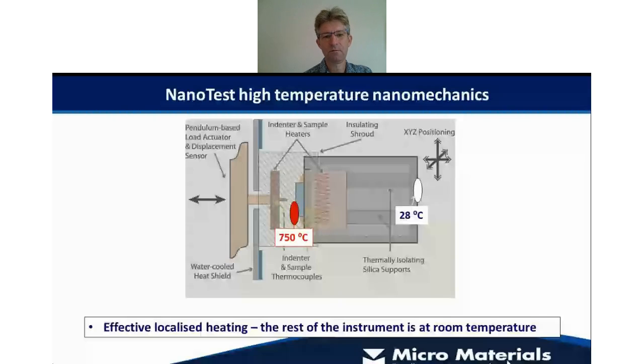We did a test at 750 degrees, and we can put another thermocouple at the back of the hot stage, and we can see that's about 3 degrees above room temperature, so that's almost exactly the same as room temperature. So this is very useful because that means that essentially we've really localized that hot zone,